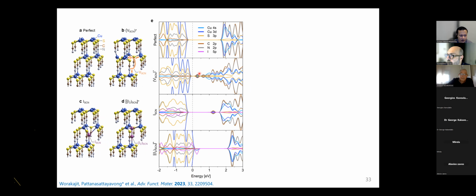Like this one here with the SCN vacancy becomes like this one here. There's still a defect state left, but it becomes much better compared to the previous case. And then surprisingly, if we can manage to add the whole iodine molecule to replace that, we could eliminate all of the donor states and actually have a very shallow acceptor state that can increase the p-type conductivity. But experimentally, we have not been able to add this as a whole molecule yet. It separates and then forms clusters of iodine.